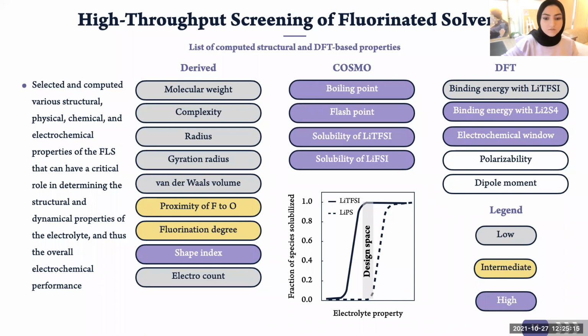Proximity of the fluorine to oxygen atoms is desired to be intermediate, because if the fluorine atoms are too far away from the oxygen, then it will result in a very high solvating power of the oxygen atom. And too low of a proximity can prevent the dissolution of the salt in the electrolyte. The fluorination degree, and also the electronegative atom count, are other metrics that can affect the solvating power of the solvent. Shape index is an indication of how linear the structure of the solvent is, and can result in improved dynamics if we are comparing 2 solvents that have the same molecular size.